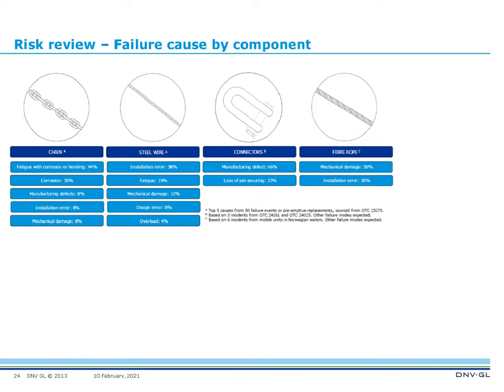The oil and gas sector has actually done quite well to aggregate mooring failure data as much as possible. And when we see the breakdown of failure modes by component, the general gist of it is that for chain, causes of failure vary, but typically it is long-term degradation mechanisms such as corrosion and wear coupled with fatigue, as I've already mentioned before.